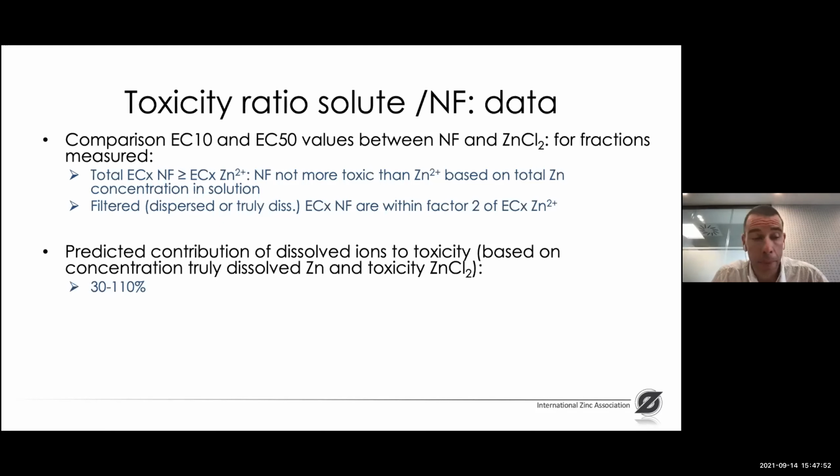Next to just these comparisons, we also predicted the contribution of the dissolved ions to the toxicity, based on what Willy presented in his presentation on this mixture toxicity approach, and based on the concentration of truly dissolved zinc measured and the measured toxicity of zinc chloride. And there we see that over all the tests done, 30 to more than 100% of the toxicity of the nanoforms can be attributed to the ions.